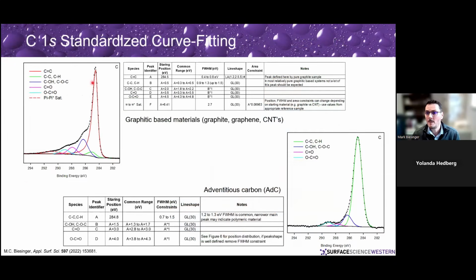And we said, okay, we want to make sure we have standardized curve fitting procedures for the carbon peak. And so we've presented different standardized curve fitting procedures for, say, graphitic materials. We want to fit this very consistently in order to get the right values and the right amounts of the different species, if you've got graphitic oxides or graphene oxides or carbon nanotubes or a similar sort of thing that will have functionality put on them. So we have fitting procedures for that. And we also have a fitting procedure for our adventitious carbon so that we're fitting that consistently, getting the right value and right positioning of that carbon hydrogen peak.